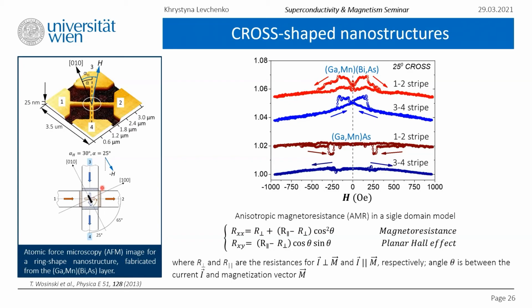Which means if the current is flowing through the terminals 3, 4, the current should overcome only a 25 degrees difference between the spins in this segment and this segment. And here we basically have one domain, domain wall, another domain, domain wall, domain. In total, we have 5 domains and 4 domain walls. The contribution to the resistance from the scattering while passing these 2 domain walls will be lower in comparison to when we measure the response from this stripe, because here it should overcome a 65 degrees difference. And it will result in states of higher and lower resistance, which would be very stable in time and can be swapped with an opposite sign weak magnetic field or just a spin polarized current.